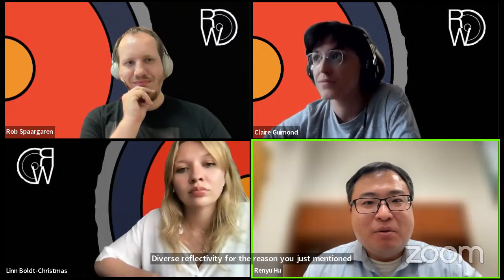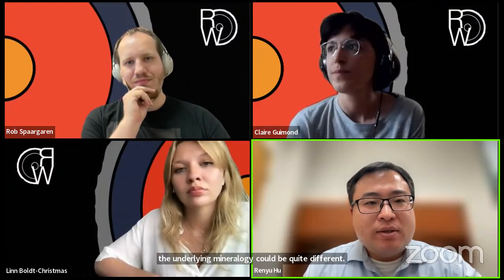Yes, so for instance, in that expanded library, we have selected a number of basalts with different underlying mineral composition, and then we measured their reflectivity and emissivity, and we did find that they have very diverse reflectivity for the reason you just mentioned. The underlying mineralogy could be quite different. But on the other hand, the Christiansen feature seems to trace the SiO2 mixing ratio in that mineral assemblage. So that's a pretty unique tracer of how mafic or felsic the whole assemblage is.